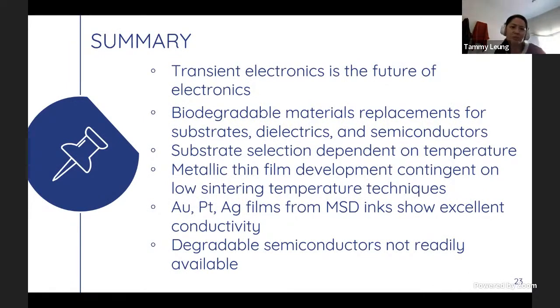So in conclusion, we have demonstrated that transient electronics can be accomplished by replacing common or typical materials with biodegradable alternatives for the substrate, dielectrics, and semiconductors. However, these biodegradable materials always come with restrictions, specifically with temperature stability, and therefore we need to use low temperature sintering techniques that are able to develop these films on top.